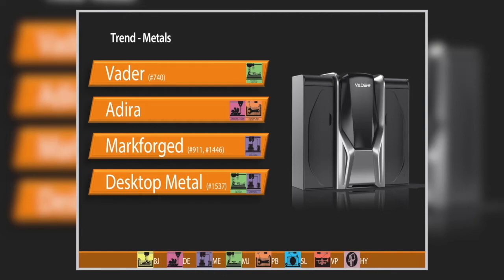What really excited me about Vader's process is it opens the door to materials previously unavailable in additive manufacturing. Two that caught my attention: aluminum in the 6000 series — 6061 — which isn't otherwise available, and the 7000 series. They're also going after speed, coming in at about twice the speed of metal systems based on powder bed fusion.